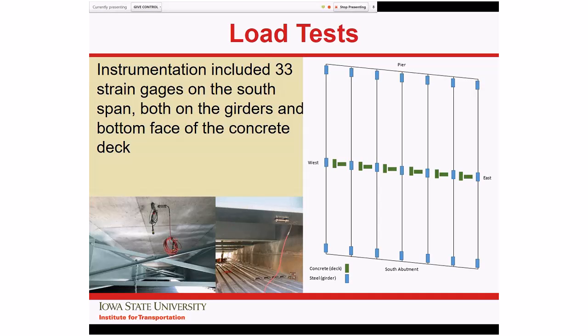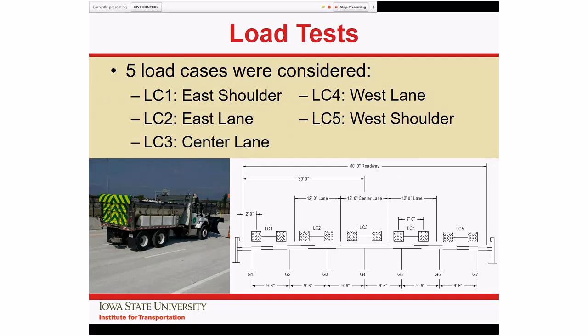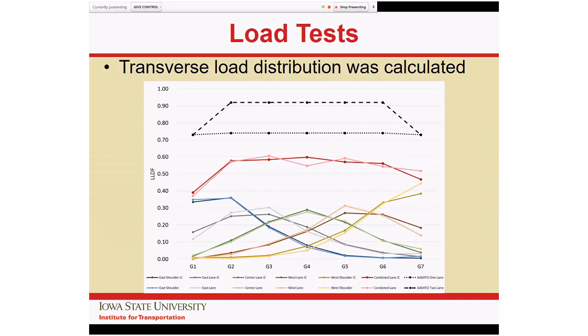We also put strain gauges underneath the bridge decks, and we did a load test. Drove a truck over the deck a week or two after the deck had been constructed. We did it in 5 different locations and measured the differential movements. And again, if you want the full details, go chew on the report, but there's not a lot of difference here. Structurally, these two decks are performing very, very similar to each other.